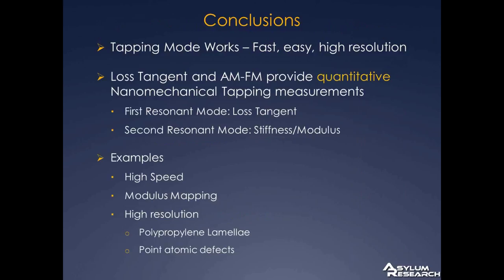The first conclusion is that tapping mode has been around forever, and the fact is it works. It's fast, it's easy, you get high resolution, it's a really powerful technique. Loss tangent and AM-FM now bring the possibility of quantitative nanomechanical measurements to these techniques. Using that same technique that you've used for your entire life, maybe, now we can look at loss tangent and we can look at stiffness and even in some cases the modulus mapping of materials.